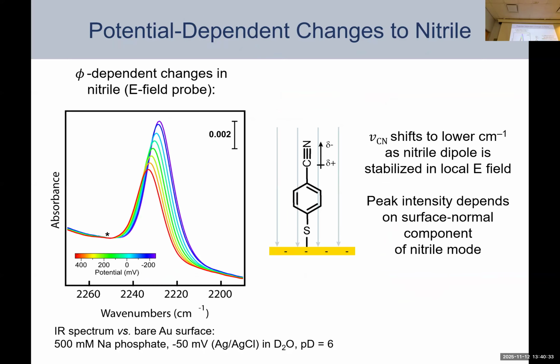I also wanted to mention this nitrile probe. So we could look at this one as a measure of local electric field. And this depends on something called the Stark effect. The Stark effect is essentially saying that if you take a dipole like the nitrile CN stretch here, it's going to be polarized delta plus to the carbon side and delta minus to the nitrogen. If you now put this in an electric field, you're either going to stabilize or destabilize this dipole, right? And so the wave number will shift, the vibrational frequency of that dipole will shift as you stabilize or destabilize this dipole.